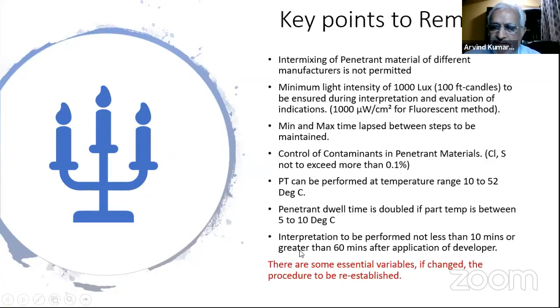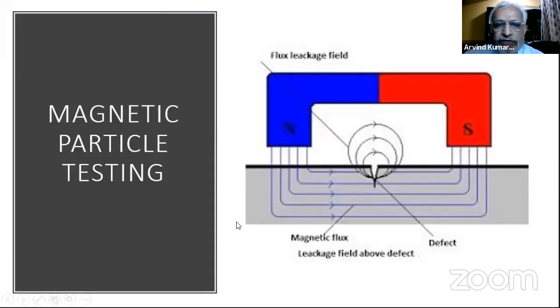Now these are the variables. Like I said, final interpretation has to be done not less than 10 minutes and not more than 60 minutes after application of the developer. So that was about PT.